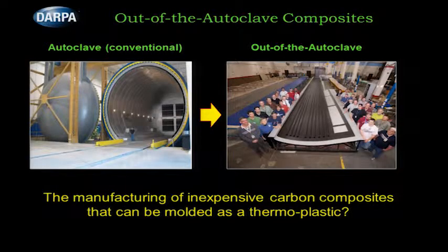But the real dream I have, and so please, someone take notes and listen and try to do this, is to take high aspect ratio carbon, if not nano, micro tubes, but maybe a fraction of a micron in diameter with tens or maybe 100 microns long, with the ends treated. You can injection mold those into any form you want, and then you want to initiate some chemistry to link the carbon rods together. You should get 80, maybe 90%, maybe 75% of the strength, but now it becomes cheap. It becomes injection molded, which would again transform how you make composite materials. Before, it's sheets and fibers. You layer it out, you put essentially an epoxy-like material on it, and you flatten it. If you can do this in all one fell swoop, again, you're in a completely different place.